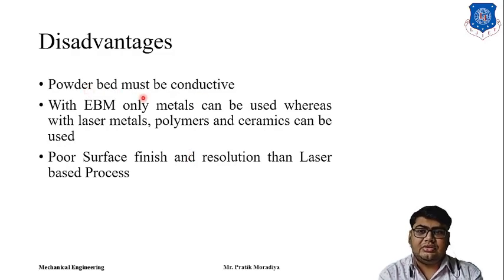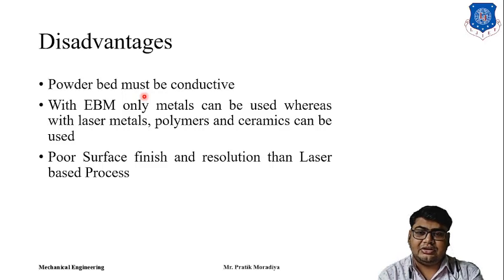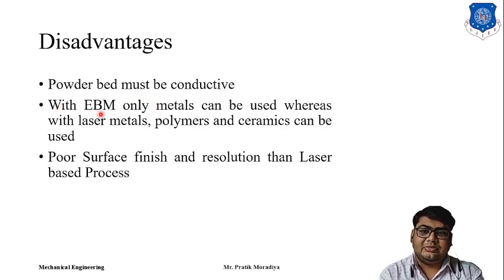There are also some disadvantages. First, the powder bed must be conductive, because when electrons strike the bed it continuously gains negative charge. This causes new incoming electrons to repel, and the powder particles themselves gain negative charge and repel each other. To neutralize this extra charge it must be earthed, so the powder must be conductive. This means with electron beam melting we can only use metals, whereas with laser we can use metals, polymers, and ceramics.